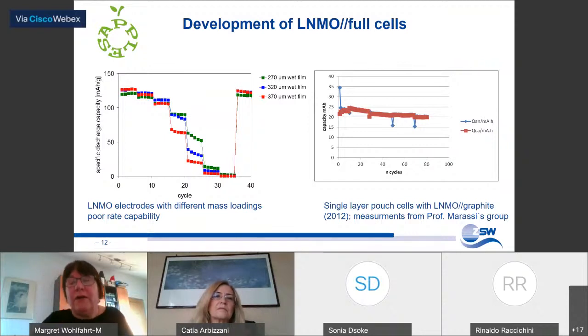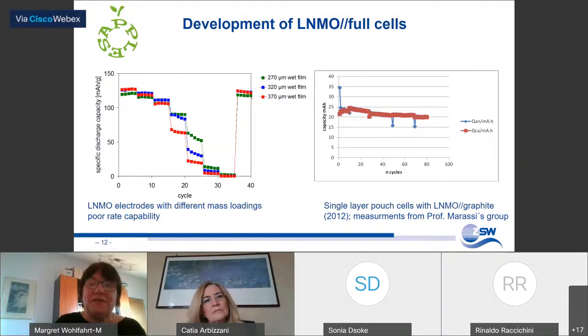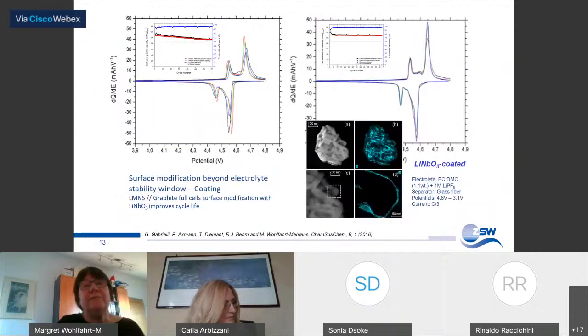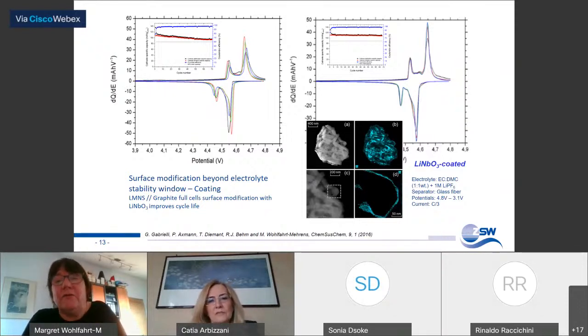But also here we were able to make a relatively, for this time, relatively stable system. And Roberto Marassi gave us some directions how to improve the material. And some years later, we were able to develop a high voltage lithium manganese spinel with quite good cycling stability, also in the full cell, and also with very good rate capability.